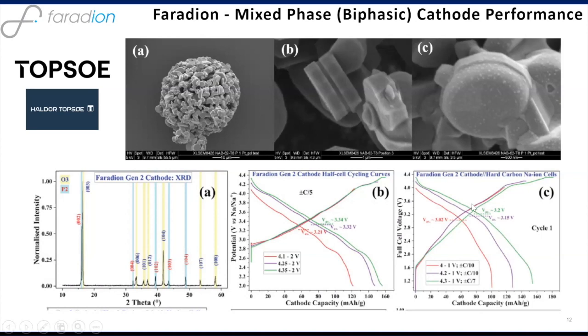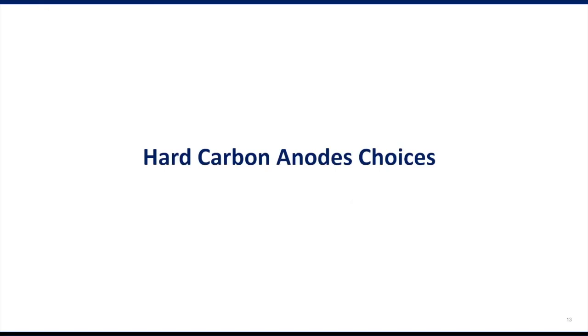On the right-hand side, we're showing that same cathode material incorporated in a full sodium ion cell with a hard carbon anode. And even with this configuration, we're showing at full depth of discharge a reversible specific capacity of over 150 milliamp-hours per gram. That's really excellent performance, right? And the operating voltage of that cell, you can probably see the average voltage is about 3.1 volts for the cell voltage. So really excellent performance from the cathode active.